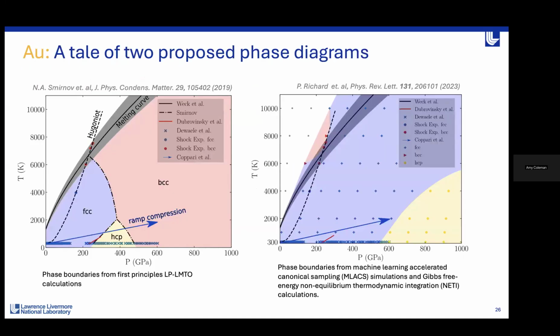Just to put this in some context, before our paper was published, there were a couple of ideas from various different theoretical calculations of what might be happening in the gold phase diagram. There's one model published in 2019 which describes a structural transition from the face-centered cubic, the ambient structure of gold, to a body-centered BCC structure at some pressure below 400 GPa.